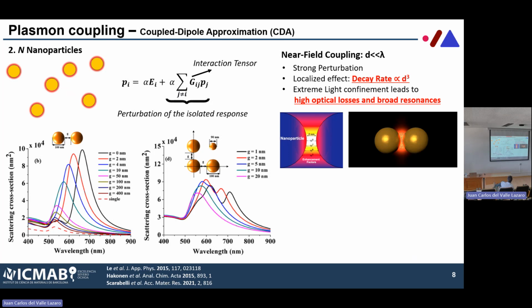One is a near-field coupling, the so-called near-field coupling, where the nanoparticles are very, very close one to the other. This is very useful because there is going to be a strong perturbation of the optical response, but this is going to be associated with very high electric fields, these so-called hotspots that we use for enhanced spectroscopies and so on. This is very interesting, but from the perspective of someone that wants to have very high quality resonances, it basically doesn't work, because what you have is extreme light confinement that is also associated with much higher optical losses, which again have much broader resonances.